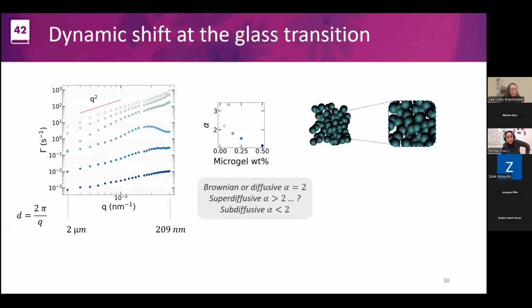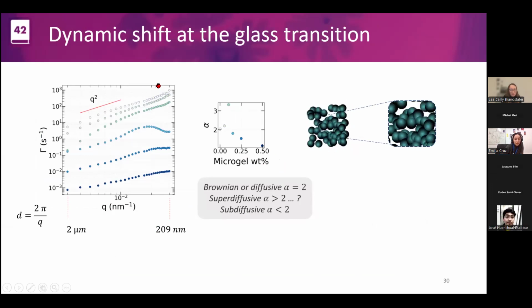Let's take a look. So first, I chose this other representation here. So instead of putting q squared here, the q squared is the power law that scales the characteristic decay rate with the length scales. Then I put some length scales here so that you can keep in mind that we're seeing different windows with the different angles here. So we're seeing higher dimension or length scale than the particle itself, and also something that's relevant to see the particle. What we see here is that when the particles were just in the solvent, they were pretty much Brownian. So there was this Brownian diffusion with a power law of 2.